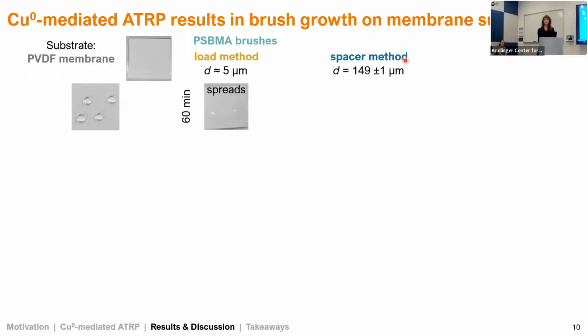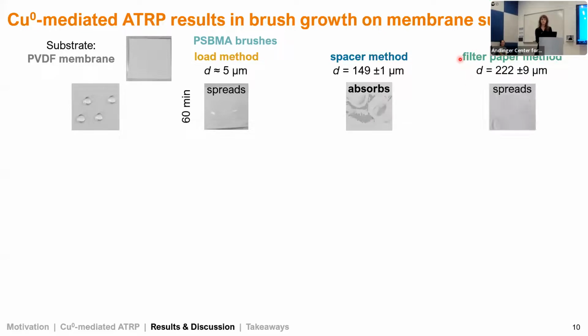For the spacer method, increasing D here, we now see that water is actually absorbing into the membrane. So you can see these transparent areas here where it's fully wetted. And for the filter paper method, here increasing D again, but also using filter paper, we see spreading across the surface, although it's somewhat more heterogeneous.